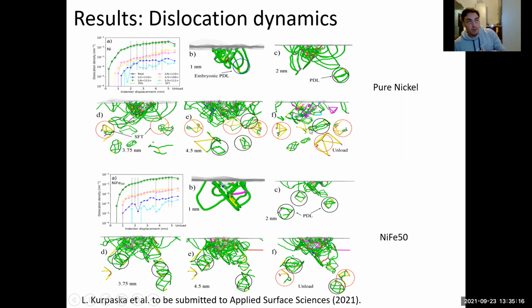And then you are doing the unloading process, and some of the prismatic dislocation loops, because of the mobility and the recovery of the material, are coming back and being absorbed by the surface when the indenter tip is coming back and doing the unloading process. So you are going to see all of this, but I also want to show you that here in the dislocation density graph as a function of the indenter displacement, you can see the nucleation of the prismatic dislocation loop, another one, and then the nucleation of the stacking fault tetrahedron. Then you have another prismatic dislocation loop, and then you have another stacking fault tetrahedron.